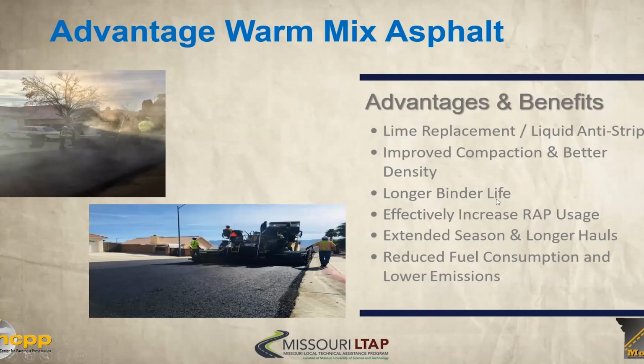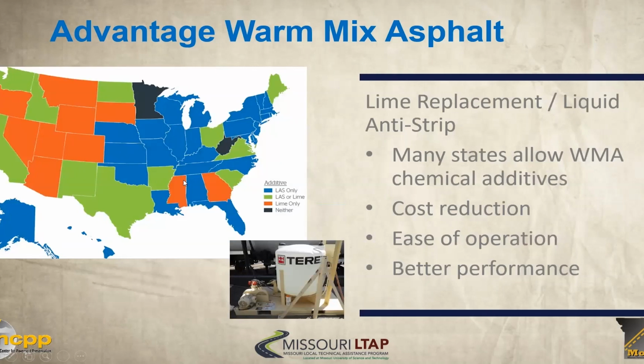So the nice thing about this is because we're producing at a lower temperature, meaning we're not heating the binder up as hot, and asphalt binder is very sensitive to high temperatures, it means that we have a longer binder life. We can increase RAP, extend the season, longer haul, obviously the green benefit. And so, here's kind of a little schematic of the types of states that use this. If you look at Missouri being a liquid antistrip only, it's not a lime state. So that means that in essence, you're getting some of these chemical additives already.